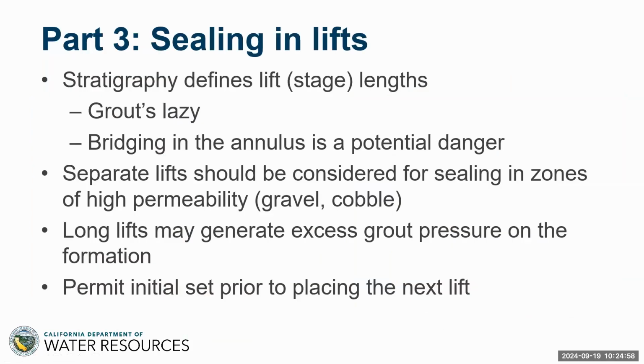Yeah. So one technique that we typically use in our grouting is sealing in lifts or stages. So if we had a hole, say, 100 feet long, and we look at what the geology is, and we found, for example, that we had a very permeable layer halfway up, then we'd grout only halfway up, because the grout's lazy. It just wants to go wherever it wants to. It's very fluid. And so there we would stop at that point, let the grout set, and then maybe even use a different grout for the next stage, thicker grout or grout with sand, for example, so that we would know that we had thoroughly treated responsively each of the different ground conditions. If we don't do that, then the grout's going to go preferentially.